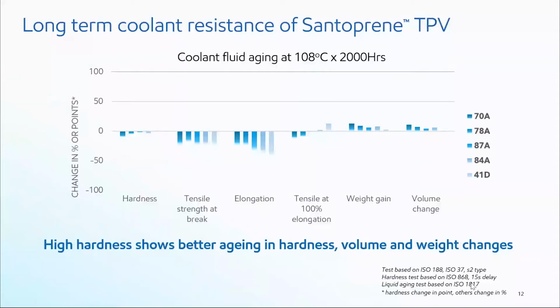And we tested a wide range of hardness from 70 Shore A till 41 Shore D. We tested 5 grades, and we tested mechanical properties like hardness, tensile, elongation, and also the weight change and volume change to see the resistance of Santoprene against the coolant. So clearly we can see that Santoprene is not aging in the coolant, and the higher hardness grades like 87, 84, and 41 show better aging in terms of the hardness, volume, and weight changes. So very minimal changes are observed even after the long-term aging in the coolant.